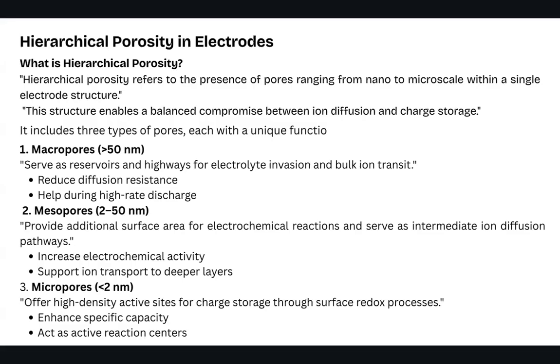The second one is mesopores. These provide additional surface area for electrochemical reactions and serve as intermediate ion diffusion pathways. This increases electrochemical activity and supports ion transport to deeper layers. The third one is micropores, which are less than 2 nanometers in size. Due to this small size, they offer a high density of active sites for charge storage through surface redox processes. This enhances specific capacity and acts as an active reaction center.